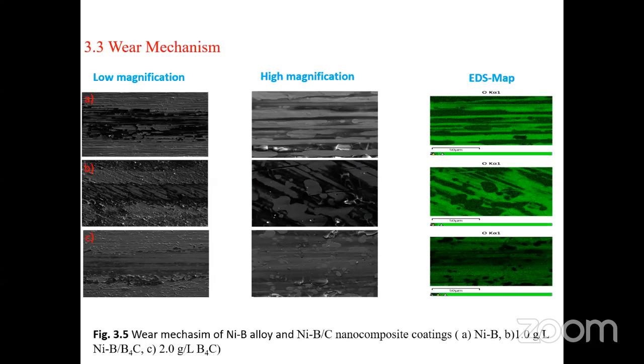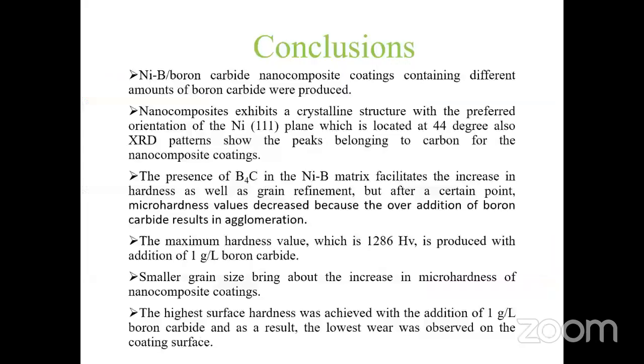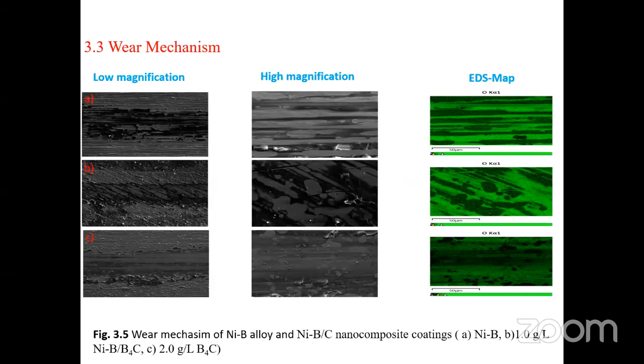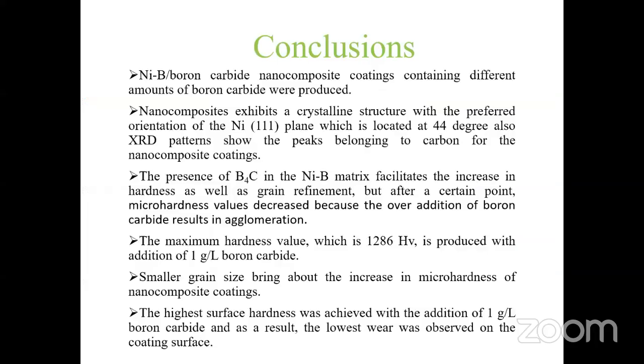With the addition of 1 gram per liter boron carbide into the nickel boron coating composition, the amount of abrasion decreased, and an increase in the amount of wear was observed with the addition of 2 gram per liter boron carbide. This is because the best surface strength is obtained with the addition of 1 gram per liter boron carbide.